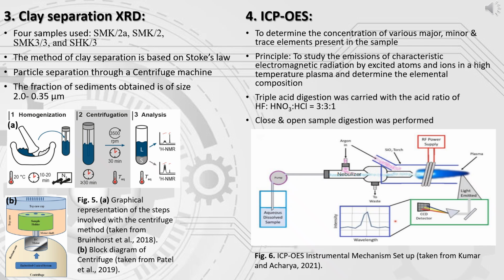The procedure was followed by closed and then open sample digestion. The samples after open digestion yield a precipitate which is sealed in a volumetric flask with 1 normal nitric acid and is sent for analysis.